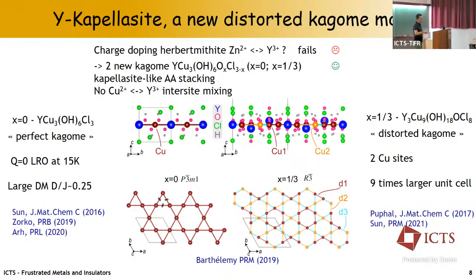And here the Kagome lattice is distorted. So we have now two different copper sites. If we just look at one layer of copper, which is represented here, the dots are copper, and there are two kinds of dots because there are two sites, the red ones and the orange ones. One of the copper sites, the red one, makes perfect hexagons. And there are two kinds of other hexagon made by the second copper site and a mixture of the two copper sites. So it's a bit more complicated model. It takes some time to get used to it, but it's quite nice.